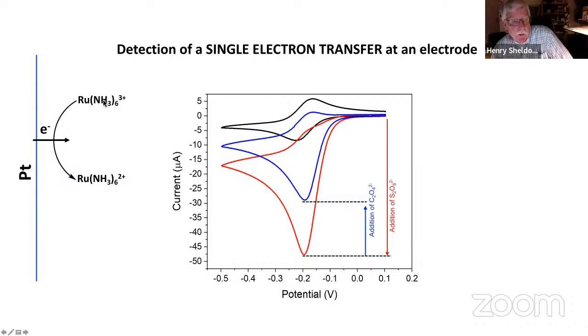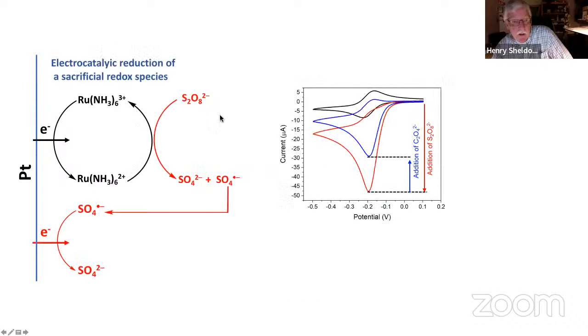So here's the first step, the reduction of ruthenium hexamine. This is the black CV, perfectly reversible curve. And then you put in the persulfate, and you get this irreversible red curve. So you're adding persulfate here. And it's irreversible now because it's a catalytic, it's an EC prime type reaction. It's a little bit more complicated because you get the second electron here. But the increase in the current from the black to the red represents the catalytic reduction of the persulfate, and then you're recycling the ruthenium close to the surface.